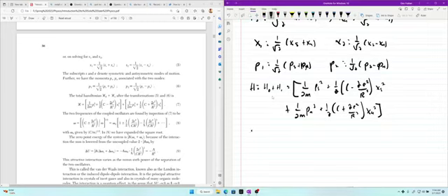The equilibrium value of R_0 is given by requiring that the U_0... Okay, yeah. So we find the equilibrium value for R, basically, and we find that it's the same for all elements within an FCC structure. So we want the ratio of the equilibrium distance and sigma to be 1.09. So for different elements, neon has 1.14, argon 1.11, krypton 1.10, xenon 1.09. And the agreement with xenon is remarkable. In other words, we're saying that for FCC, we should get this value of 1.09, and here we see that we basically do.